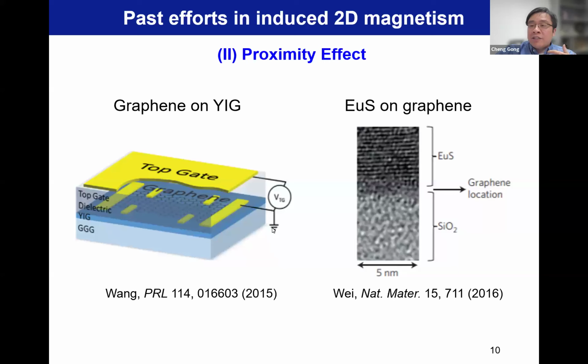But you can see this is an extrinsic effect. Certainly, the exchange interaction is not simply established because of the pi electron in carbon, but is mediated by the substrate. And meanwhile, of course, in terms of device application, you probably need to carry the whole stack to maintain the magnetic property in the so-called 2D magnet. But here is certainly not an intrinsic 2D magnet.